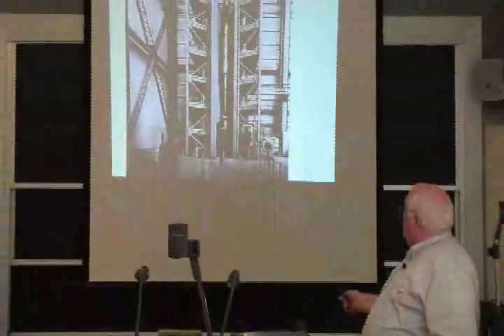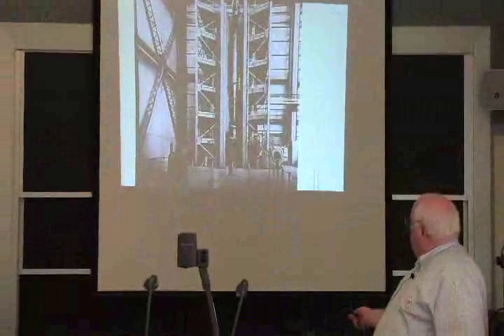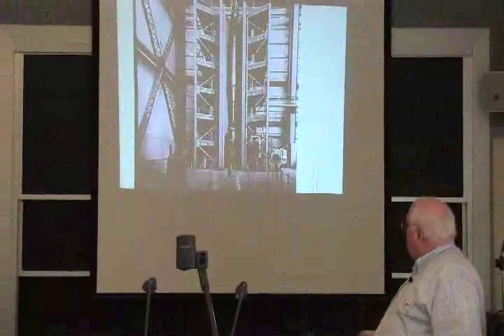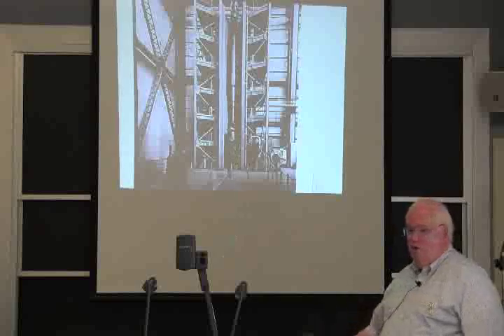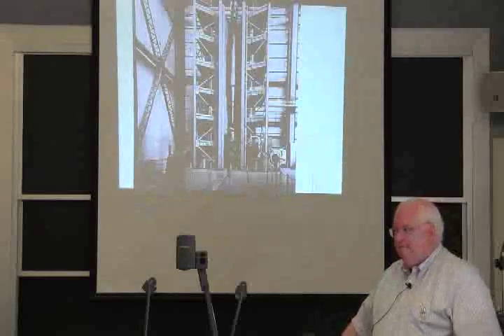At this point, it started out as about a 450-ton forging. By the time you forged it and lost all the oxidation, because you had to leave it in the furnace for a week before you got it up to forging temperature, you grew an oxide scale like an inch thick, and when you forge it, that all comes off. So you have a lot of waste, and then you machine it and heat treat it. This was basically the same system used to make battleship gun barrels in World War I.